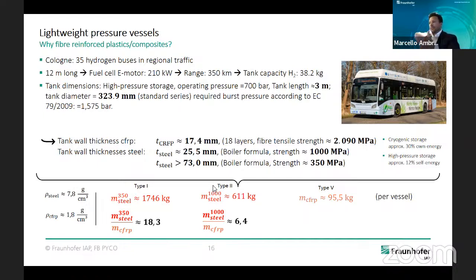And when we do the same technology, or the same pressure vessel, with the type 5, we will reach almost 100 kilograms of weight per vessel. So as you can see here, the fiber reinforced pressure vessel is up to quite 20 times lighter than the full metal one and 6.4 times lighter than the type 2.